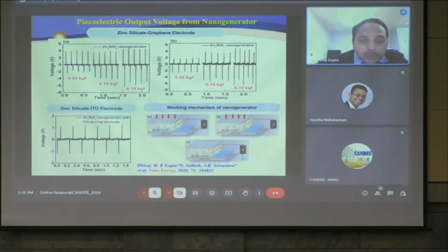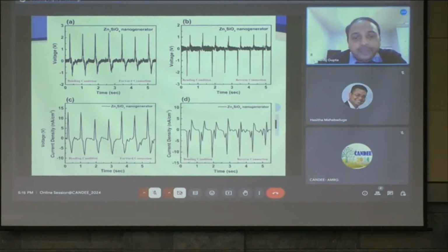And now we also compare the performance with the ITO electrode. See, with the ITO electrode it was just 1 volt, and with the graphene it was very high. It means that the charge transport was also efficient at the interface of the zinc silicate and the graphene. And since the device was flexible, we can fix the device on any part of our body and sense it.